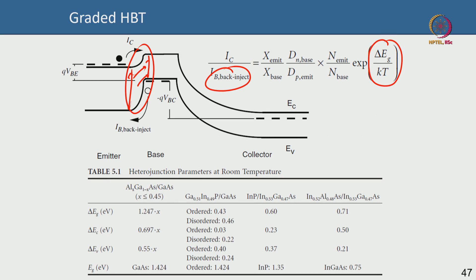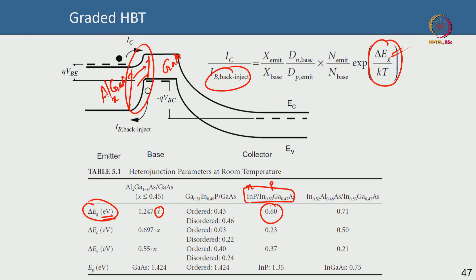In this table, the higher the discontinuity between the emitter and the base, the better and higher will be the beta, because this quantity governs it. In an AlGaAs/GaAs heterojunction, the band gap discontinuity will be 1.247 times x, where x must be less than 0.45 because above that it does not hold. Similarly, indium phosphide and indium gallium arsenide — 53% indium, 47% gallium arsenide — is a classic emitter and p-type base combination giving 0.6 electron volt of discontinuity between emitter and base.